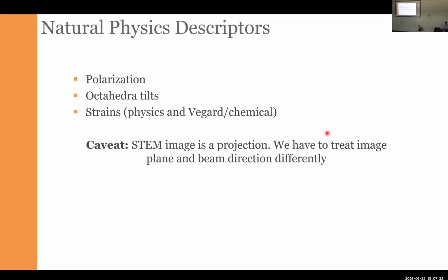For example, if you have the mistilt effect, it basically means that one part of the image is tilted slightly differently than the other part, but you can expect that the mistilt will create some form of smooth gradients within the image. And if you start to see something that has a periodicity of double the unit cell, then that's not a mistilt effect. It cannot be.